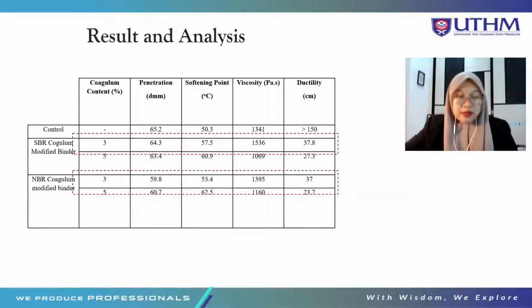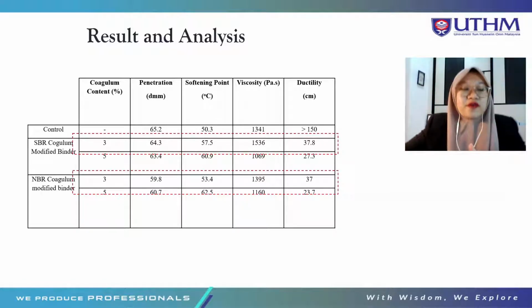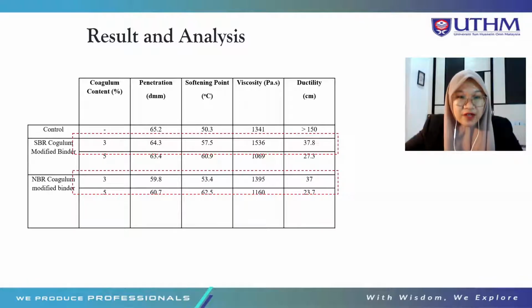Next, this table shows the summary of results for all the samples tested. The optimum modified binder for both SBR and NBR coagulum asphalt is 3%. Based on the results obtained, the penetration, softening point, and viscosity for 3% and 5% concentrations of both SBR and NBR coagulum modified binder show only slight differences from asphalt binder with zero concentration. Meanwhile, the ductility results show a huge difference from the control binder. Thus, due to the ductility, the appropriate amount of both coagulum modifiers to use in asphalt binder is 3%.